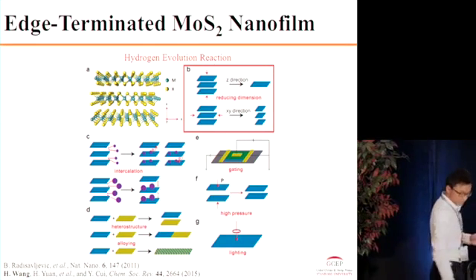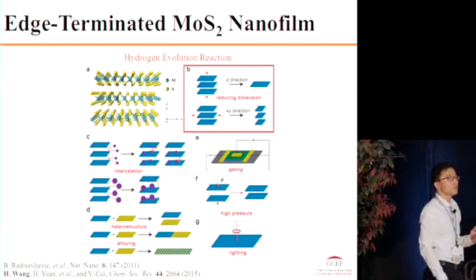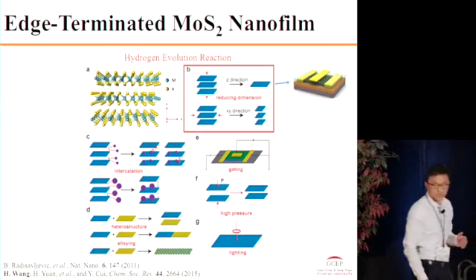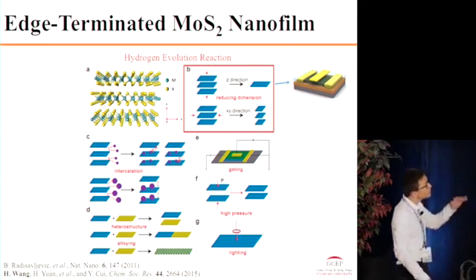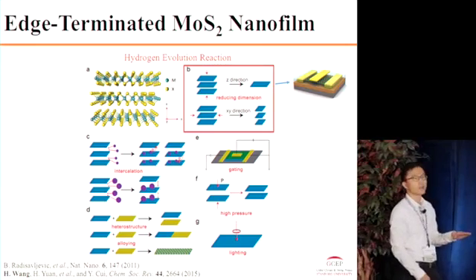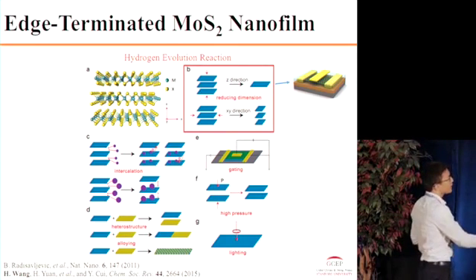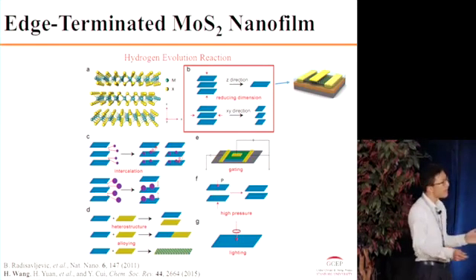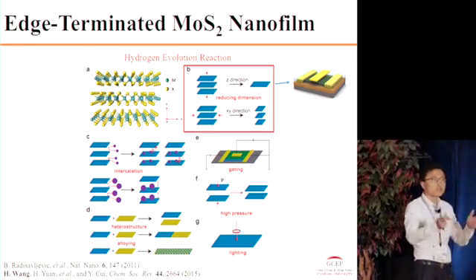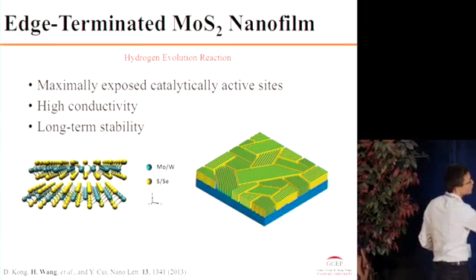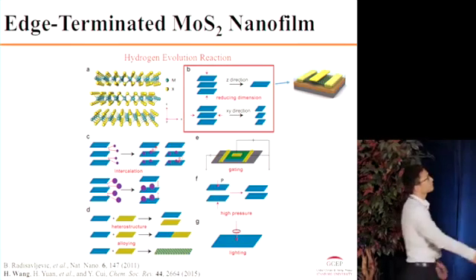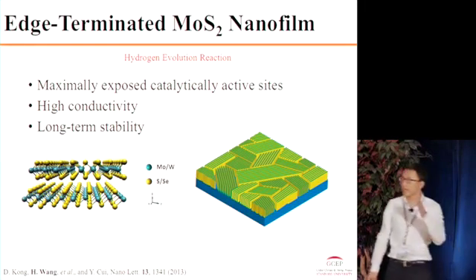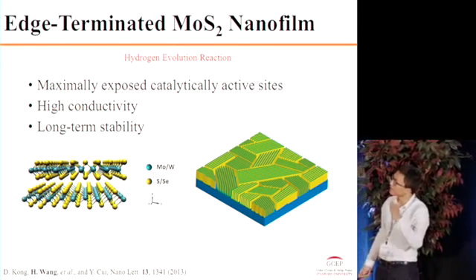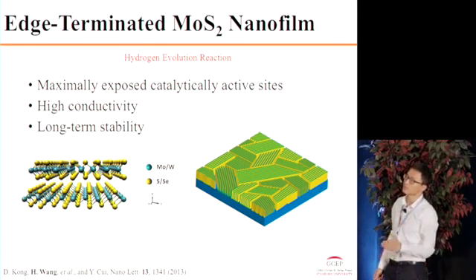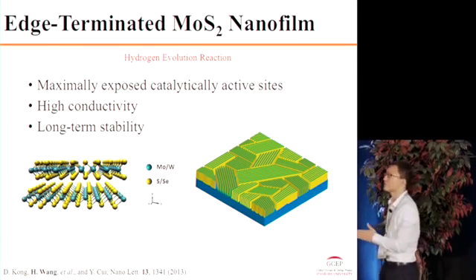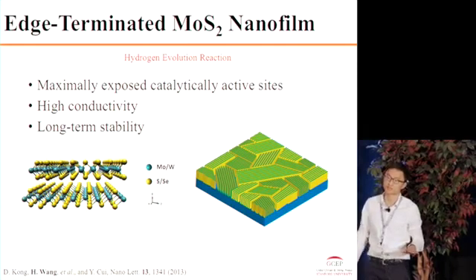A lot of research came from the discovery of graphene as a 2D material, where people thin down the 2D layered material through the Z direction to obtain single atomic layer molybdenum disulfide to do their transport measurements. But in our case, we want to expose more and more edge sites, so we are trying to reduce the dimensions through the XY direction. Our ideal structure is a molybdenum disulfide layered structure with the layers vertically standing on the substrate, which will help us expose 100% of the active sites on the surface.